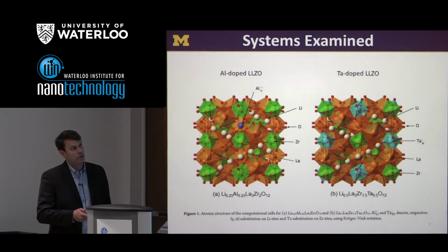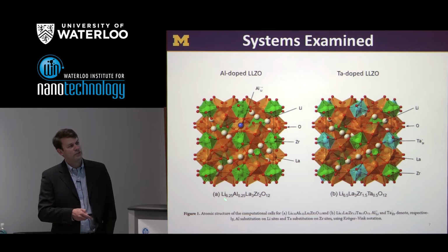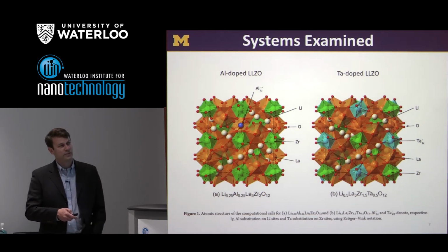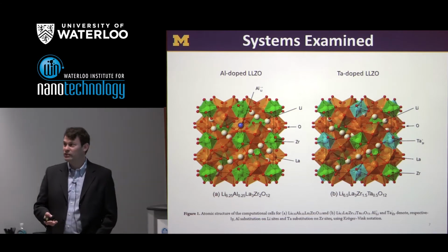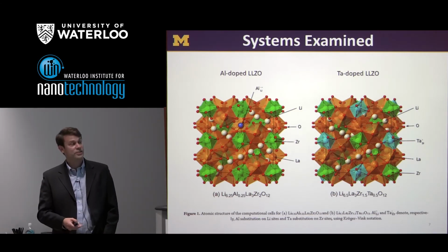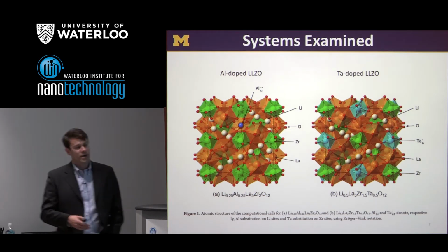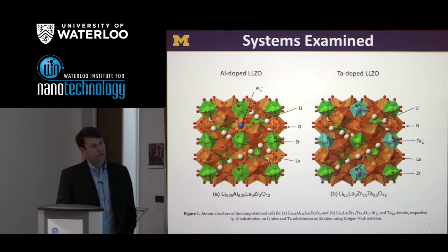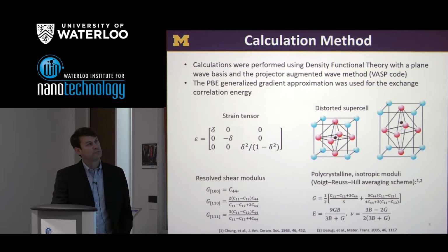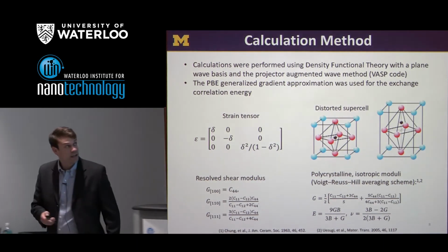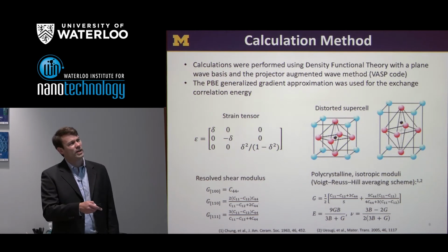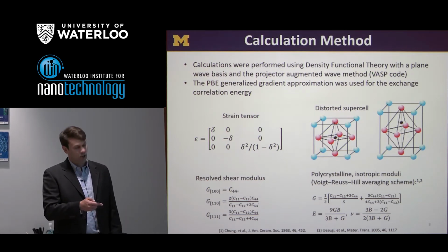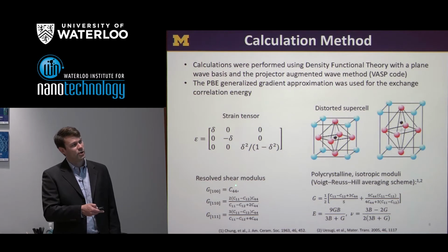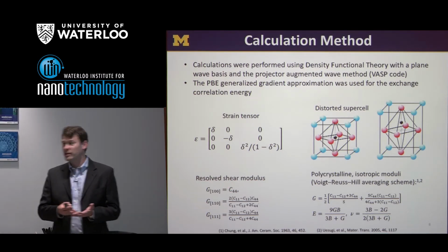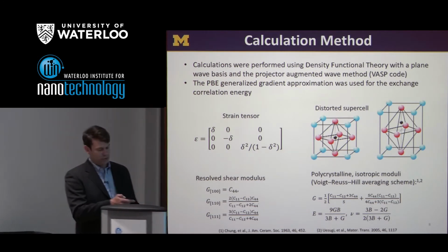So here are the systems we're going to focus on. These are LLZO with some dopants, either aluminum or tantalum. These are aliovalent dopants, which basically create more vacancies on the lithium sublattice, again possibly resulting in higher conductivity of lithium. In fact, that's what happens. These are generally agreed to be 2 of the highest conductivity compositions, so these are what we've used in our calculations and in the measurements. A calculation using density functional theory, which is a quantum mechanical method, was performed to evaluate all of the elastic constants of LLZO. This is a cubic material, so we have 3 elastic constants we care about: C11, C12, and C44.